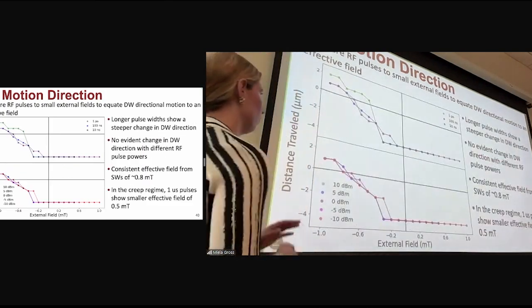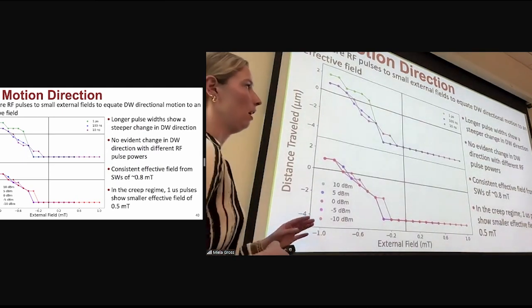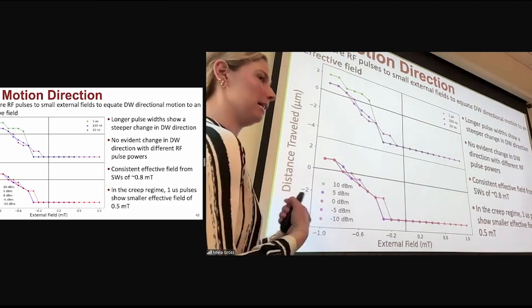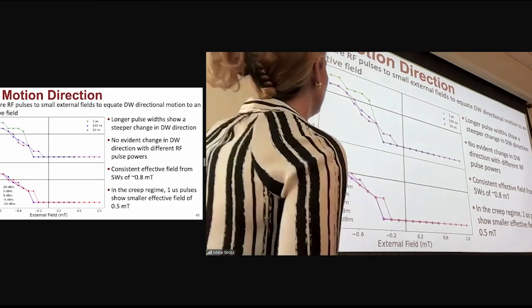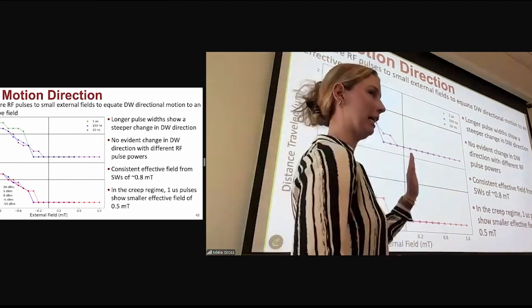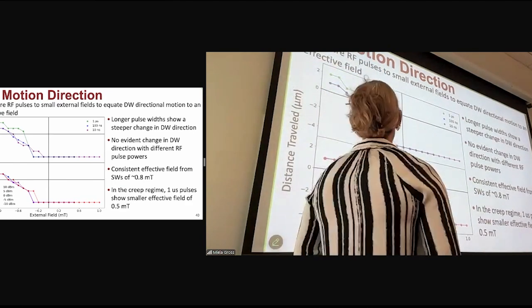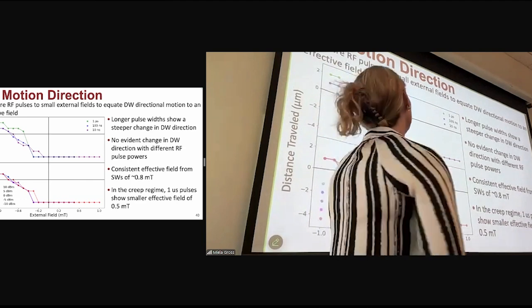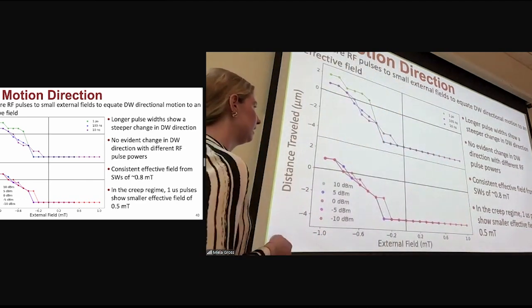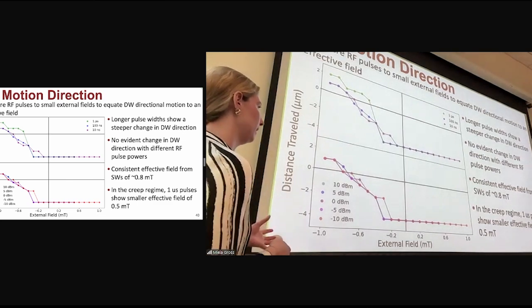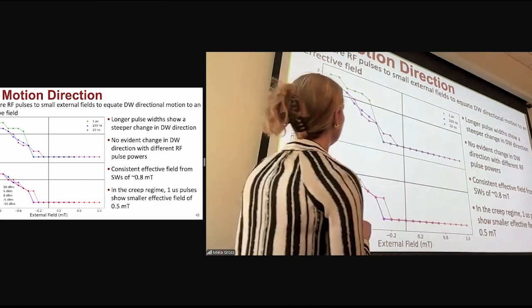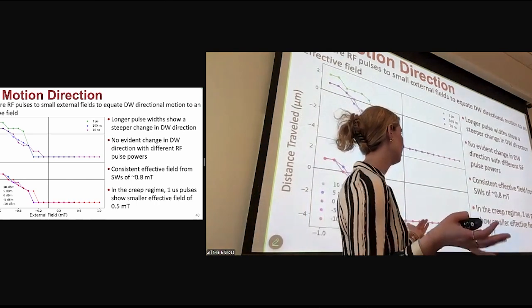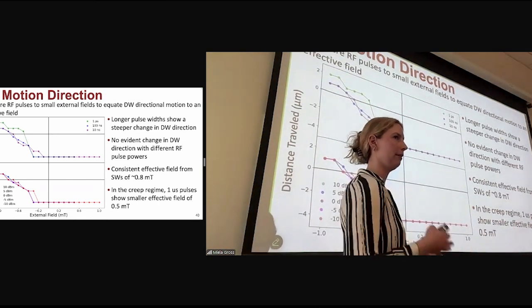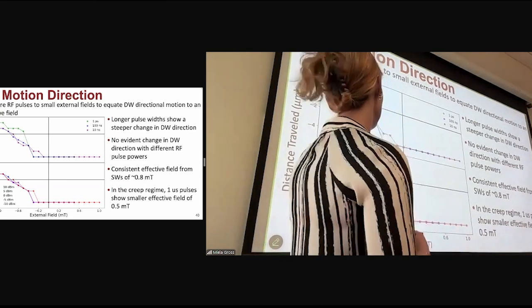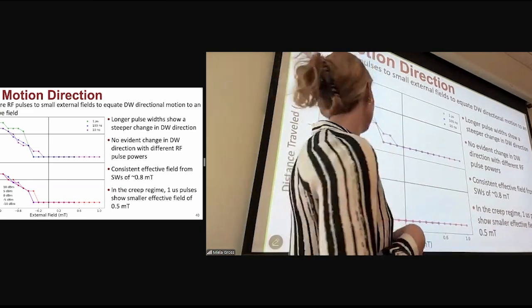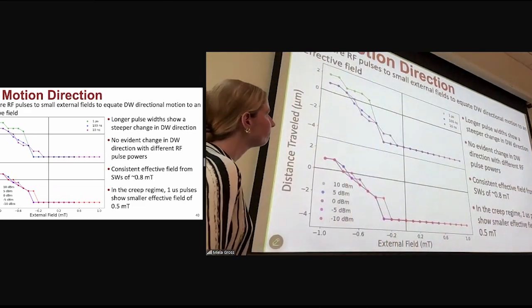But I wanted to change the pulse width and also the pulse power to show how that effective field and how those competing effects also might change. And so with the longer pulse widths here, you see a steeper change in the domain wall direction. However, with increasing powers, we actually didn't see any changes. But across the board, you see a consistent effective field of about 0.8 millitesla from the spin waves. The only outlier here is the 1 microsecond pulse width, and that has a smaller effective field of 0.5 millitesla. And it's the one condition that was in the creep regime versus the constant energy regime. So it might have some other thermal effects going on there.